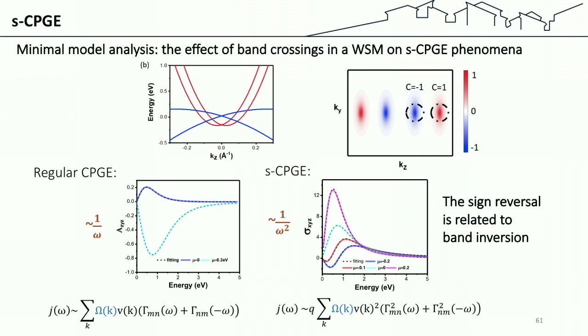Interestingly, because the response function is related to the Berry curvature of the system, this response, compared to conventional CPGE, has the square of the band velocity term. As I said, one important aspect of these topological materials is band inversion. Because of this band inversion, V goes to minus V, omega goes to minus omega, but because this is V squared, the minus remains, and the current direction changes in the vicinity of the Weyl cone. But not in conventional CPGE, because you have omega times V, so both become minus, and the response does not change. So this technique, in principle, can also probe the band inversion regime, where the bands are inverted.